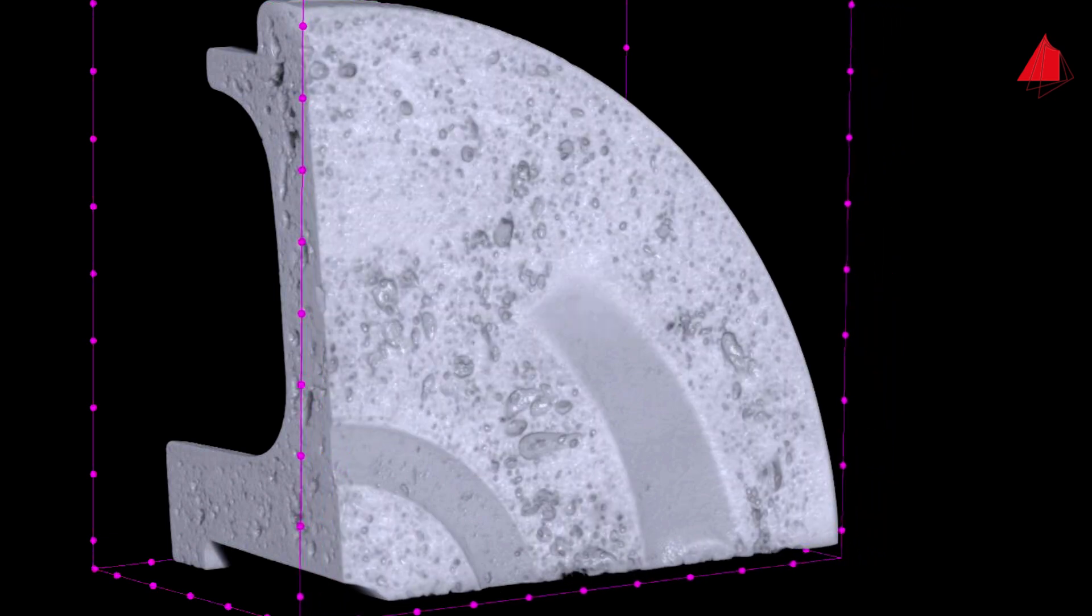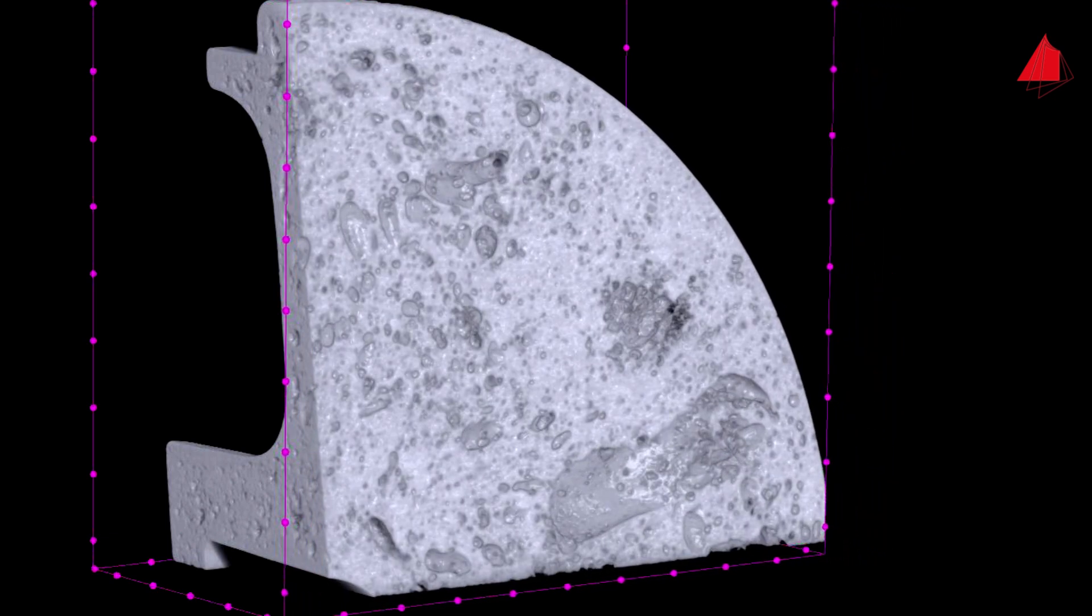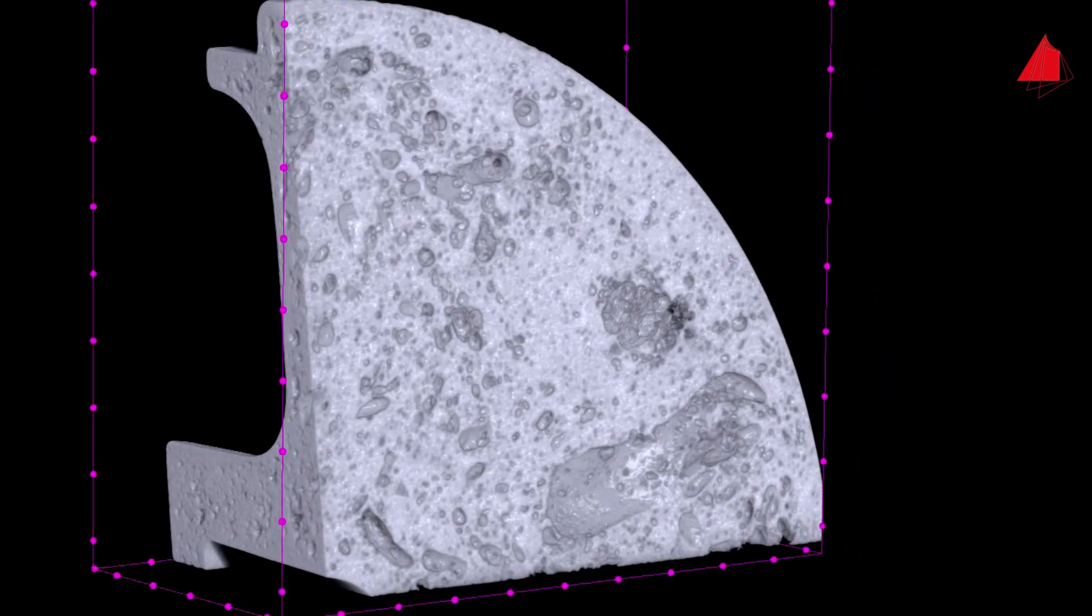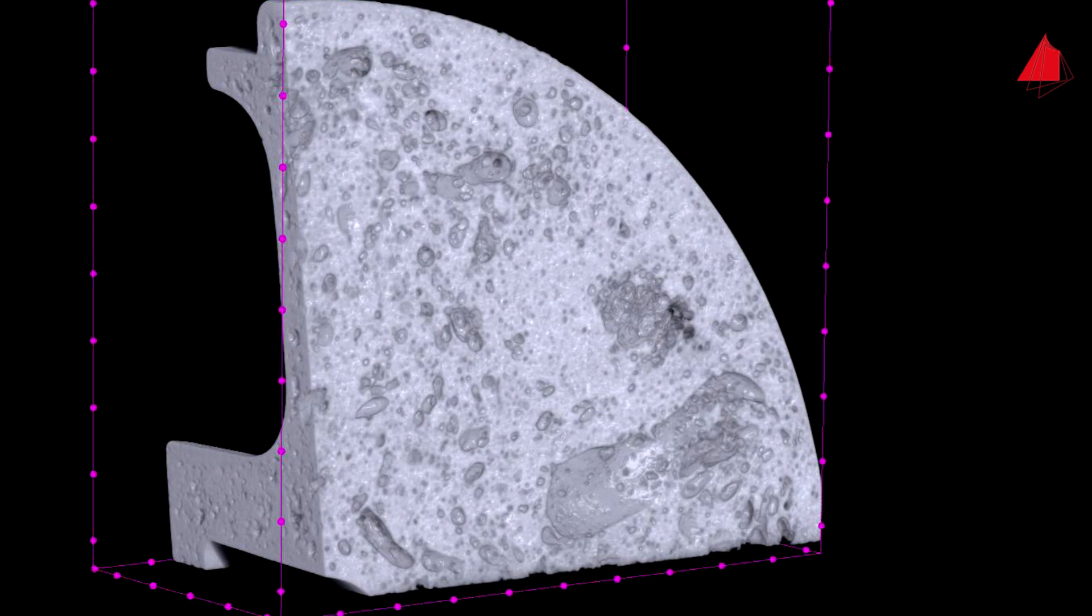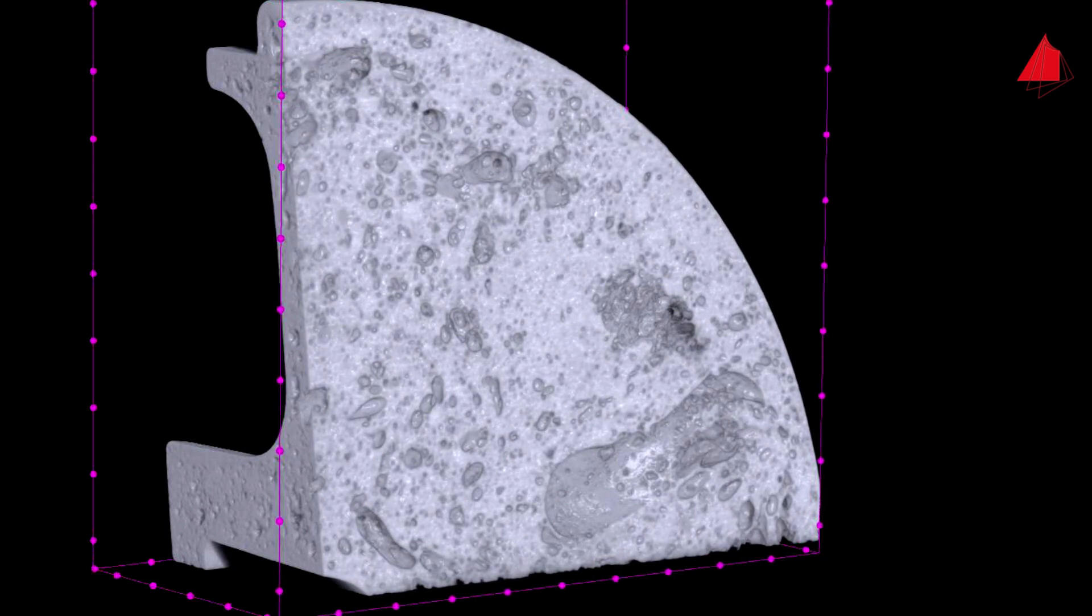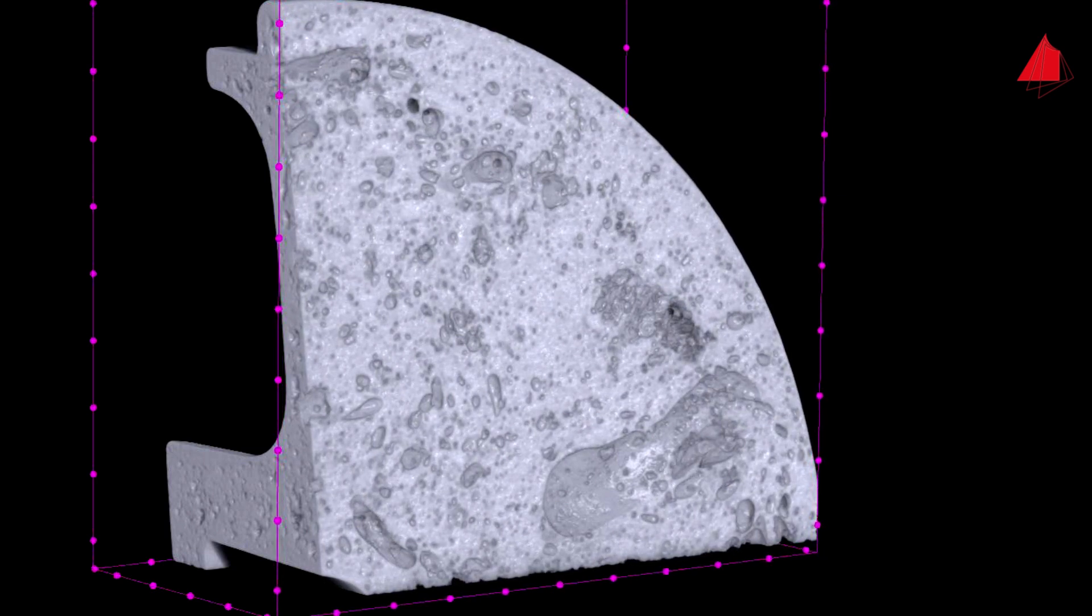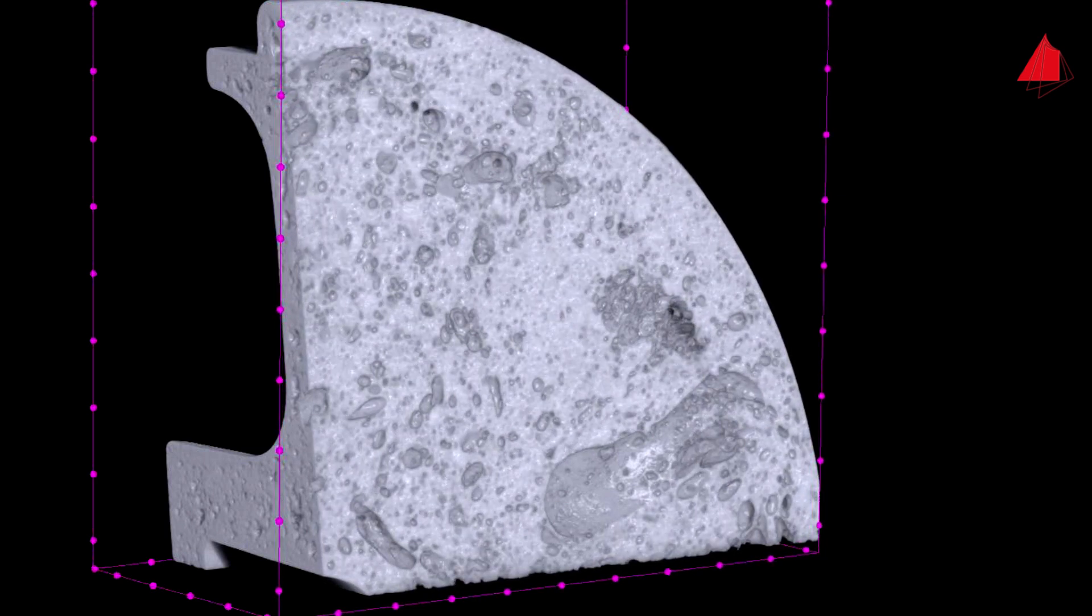The pores are filled with air that has been trapped in the course of the die casting process. The venting of the die has not been good and has led to a great number of large air inclusions.